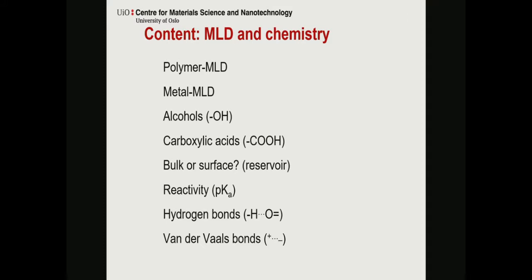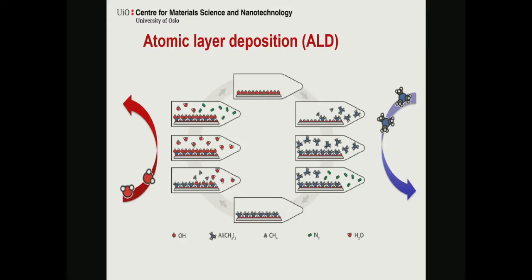But before we go much deeper into it, this is my version of the ALD. So Christoph, very nice of you for the introduction here, so I'll be brief. It's a cyclic manner, and we're exploiting the chemistries that are on the surface. This is the traditional aluminium oxide by trimethyl aluminium and water. And the fact that you then saturate the surface, here you even see some unreacted hydroxyl groups on the side. This perfect reaction here, if you dig into it, you'll find that it's not really that perfect.